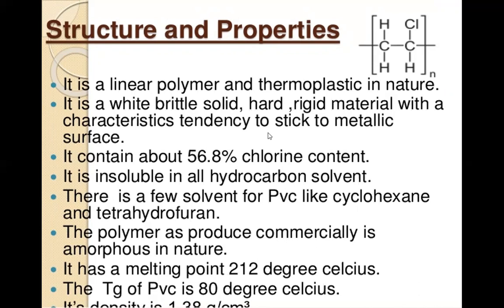And in the polyvinyl chloride structure, the chlorine composition is 56.8%. And coming to the solubility, it is insoluble in all the hydrocarbon solvents.